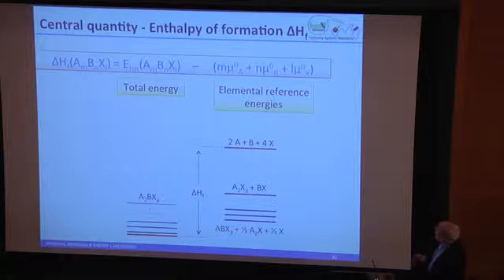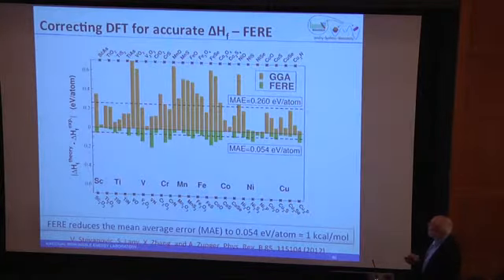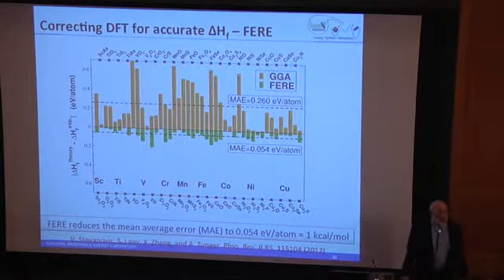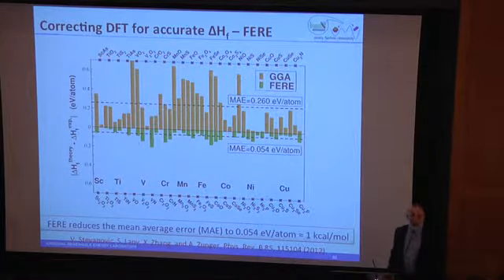So once we do that, then we have to look at elemental reference energies, which means we have to calculate versus the chemical potential of the constituent elements. This turns out to be both hard and not so hard. So it's hard because if you use DFT directly, you're kind of hosed. You can see that this is per atom. So if you look at eV per atom and you just use DFT or GGA, basically, it's hopeless. The information you get isn't going to give you any decent thermodynamic information.